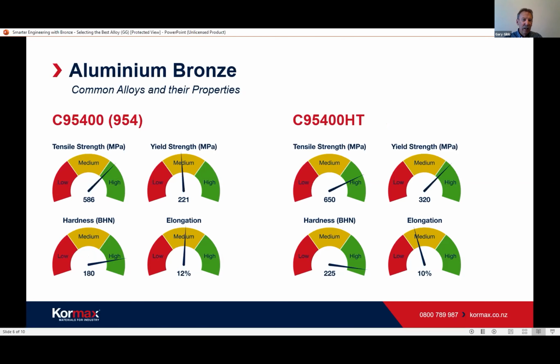So harder wearing stuff. The next ones we come to are the aluminium bronzes, or if you're in the USA, they're called aluminum bronzes. They are somewhat newer alloys compared to the others. I think a lot of them were developed during World War II. The real common one, and I'd call it the LG2 of aluminium bronzes, is C954, or we call it 954. Once again, you can see the strength's gone up, the yield strength's gone up, but our hardness has gone up quite a bit. Now, in this case, the hardness is important because with a mild steel shaft or similar, you're pretty much limited to about 150 Brinell.